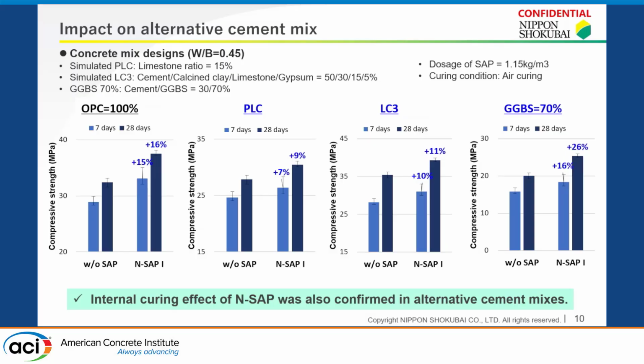And in this slide, we evaluated the internal curing effect of N-SAP I within three different alternative cement mixes: PLC, LC3, and a mix with 70% GGBS, ground granulated blast furnace slag. And we utilized Japanese raw materials to simulate these mixes due to their availability.